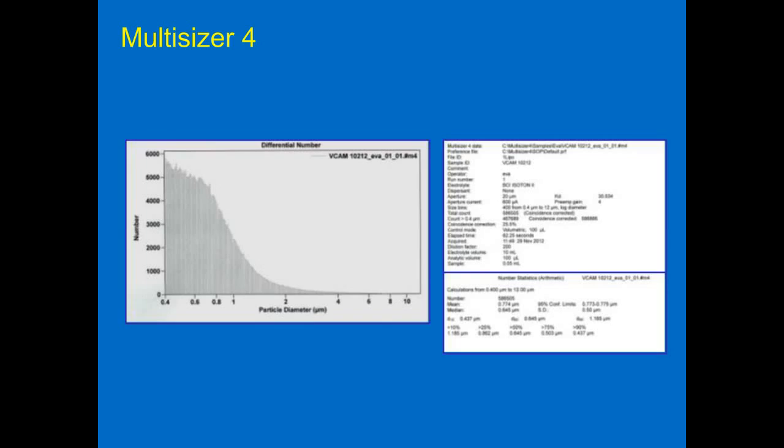And then you start the much larger population of the small liposomes. And so we have found that the median, can't really see it here, is the closest to the actual mean of that larger distribution, because you're looking at a combination of the two populations. And so in this report, it's 645 nanometers.